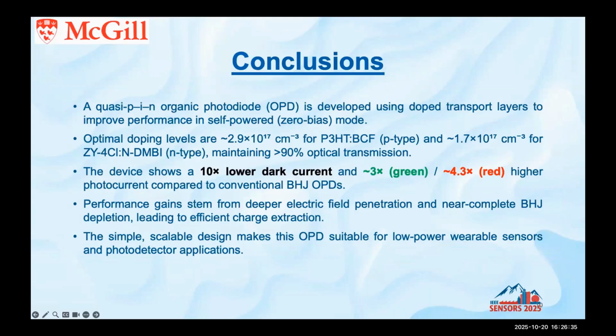Overall, quickly speaking, we developed a design by adding doped extra layers, and it shows improvement in performance in self-powered mode. They have optimized doping levels, and we designed and optimized for an optical transmission of 90%. The dark current reduces by 10 times, the green photocurrent increased 3 times, and the red photocurrent increased 4.3 times. The performance gains come from the deeper electric field penetration that we got in the new design near the edge of the active layer. And at the end, this simple and scalable design can be used for further applications. Thank you so much.